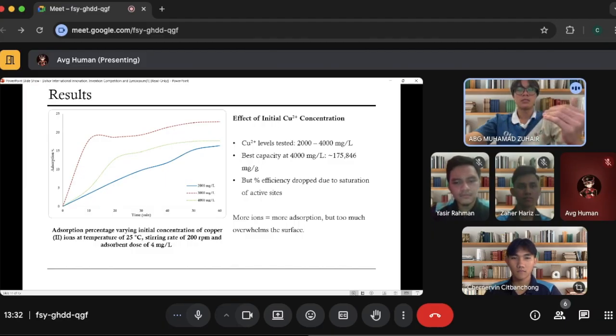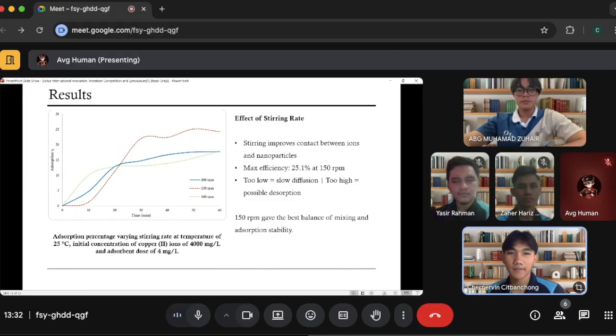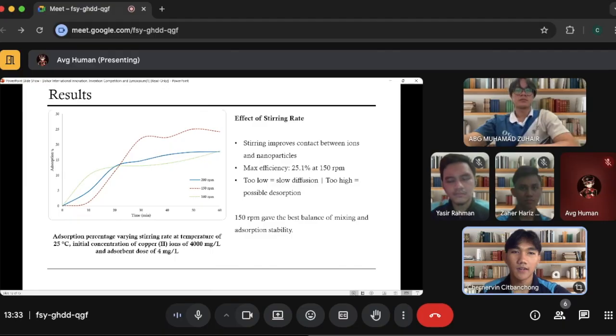However, when increasing the concentration to 4000 mg per liter, the active sites are limited, so the adsorption efficiency drops slightly. The next variable is the effect of stirring rate, which was tested between the range of 100 to 200 rpm. The mechanical force enhances the collision between copper ions and nanoparticles, thus increasing the adsorption performance. However, at the lowest stirring rate, in this case 100 rpm, the adsorption performance is the lowest, which may be due to the slow diffusion of the molecules. Increasing the stirring rate increases the adsorption efficiency. From this result, the highest stirring rate also reduces the performance, which is expected due to desorption of copper ions from nanoparticles. The optimal rate was 150 rpm, balancing diffusion and adsorption stability.